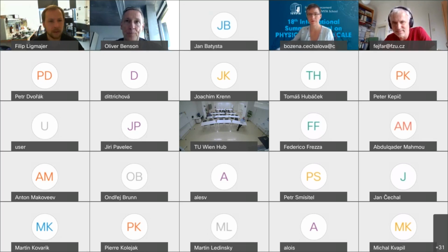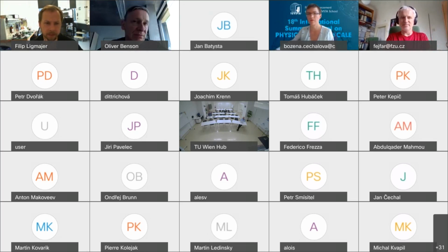Okay, thank you. I have a related question. How many defects is on average in this one nanodiamond crystal? Yeah, here we had, in the small ones, maybe a little bit less than 10%. So you use irradiation to enhance the number of defects in them, and then some heating to make the nitrogen and the vacancy find each other. But for the sample we had, it was about 10%. So we first do a characterization of a lot of these nanodiamonds on a microscope. This we can do in an automated way. Then we find a good one, then we pick it up, and then we put it on the structure.